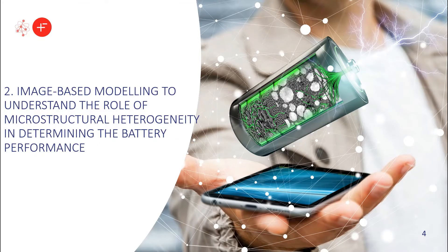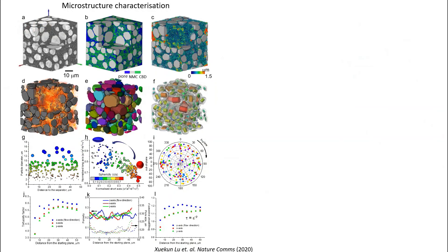Assisted by this dual scan superimposition technique, we can now explore the 3D microstructure and battery performance relationship. Visualizing the 3D microstructure of NMC electrodes, we can now see the uneven distribution of the pore morphology and size. Conducting the CFD simulation, the ion flux shows that some regions have really high flux, corresponding to locally low porosity and pore diameter regions.